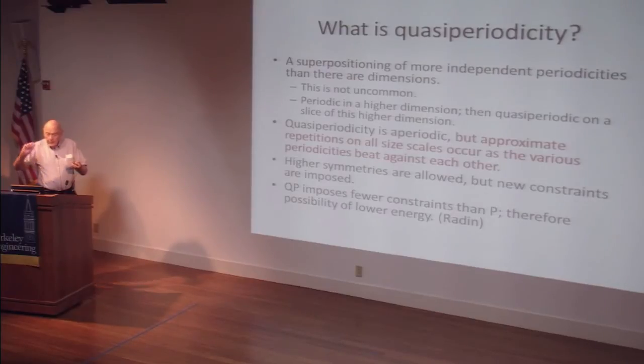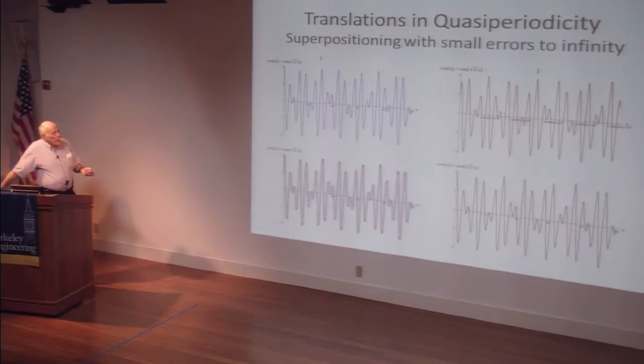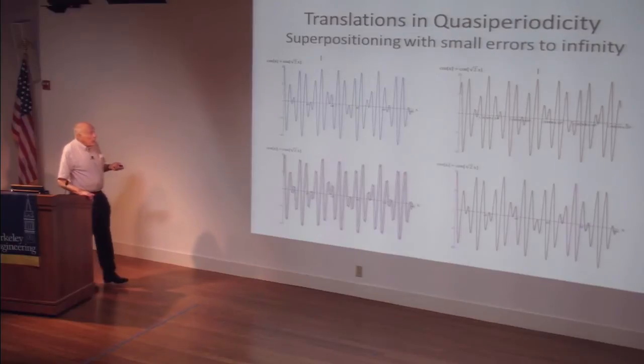So if you randomly reach into a box of interaction parameters, you almost always get quasi-periodic. You have 0 probability of getting an interaction, and he sort of says, what is it? Is it that you make the periodic lattice because of kinetics, that layers repeat, and then it has no chance of transforming to the truly lower energy? But here is an example of quasi-periodicity.